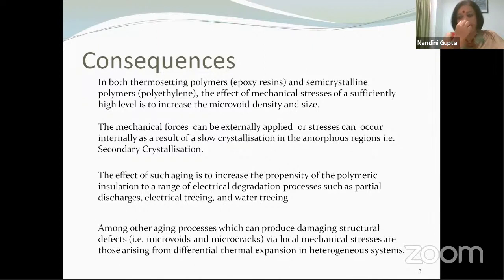Munmun, who gave a lecture and showed you a lab demonstration on partial discharges, is working on electrical treeing, and she has seen that as she continuously thermally ages the material, there are voids which are incepted in a virgin material, and then these voids increase in size. And why do we care? We care because when you have a large number of voids incepting and these voids increase in density and size, other degradation processes begin to happen.